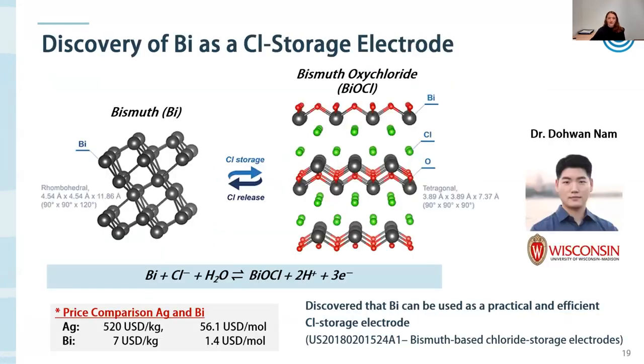My co-founder, Dr. Dohwan Nam, in 2017 screened a variety of different candidates that we might be able to use as chloride storage materials, and he found that bismuth metal can be used as a practical and effective chloride storage material through the reversible electrochemical conversion between bismuth and bismuth oxychloride, which I'm showing here. We patented this discovery in 2017, and I'm showing in this table that bismuth is much less expensive than silver. And so we were really excited about this discovery, and it allowed us to really start to investigate the possibility of developing a practical desalination battery.